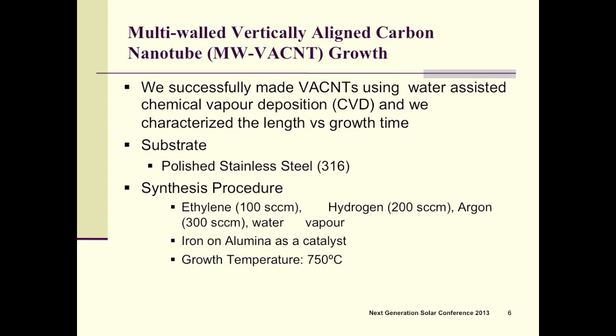And here is one of the methods, the water-assisted CVD method, to grow carbon nanotubes. We also characterized these carbon nanotubes, length versus growth time. In this method, ethylene with water vapor is the carbon source gas, the growth temperature is 750 degrees, the catalyst is iron on alumina, and our substrate is polished stainless steel.